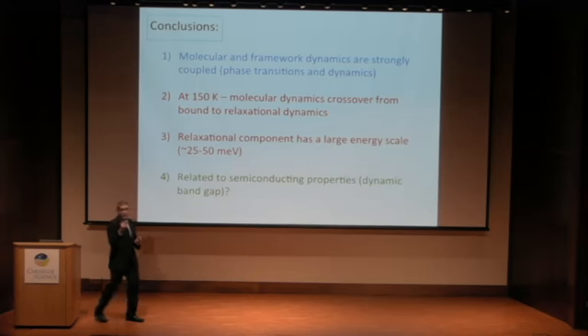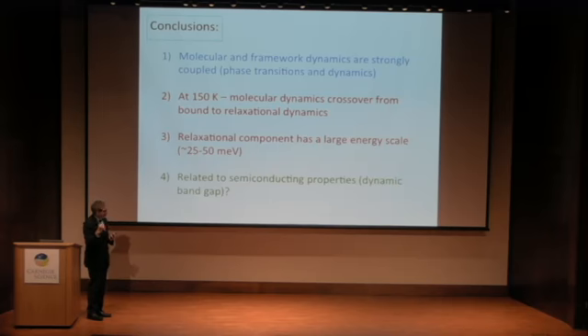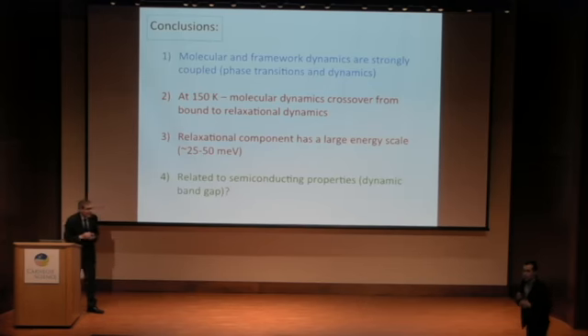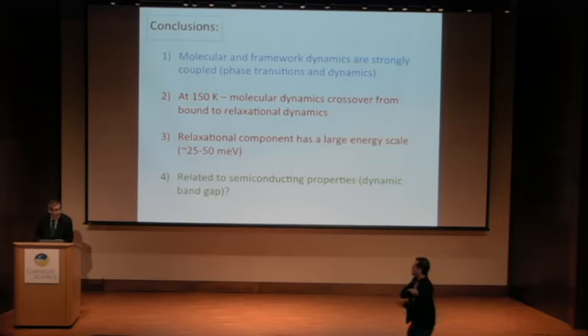So for some reason, it seems that the orthorhombic phase actually traps the molecule in an orientationally ordered position. And then once you go to the tetragonal, it becomes happy. It comes sort of free to rotate any way it likes. And that doesn't change when you go to the cubic phase, actually.